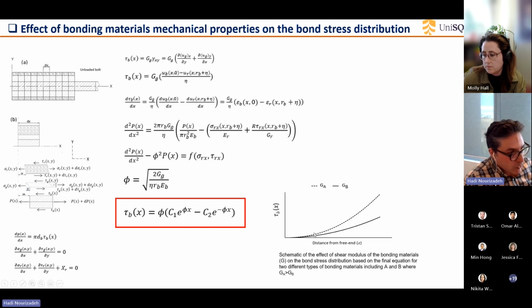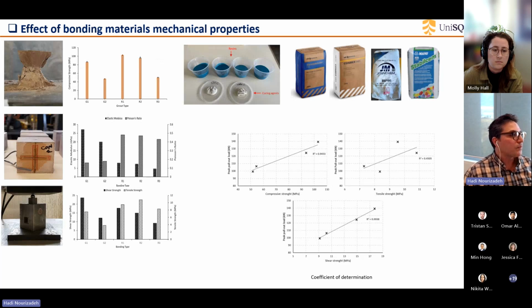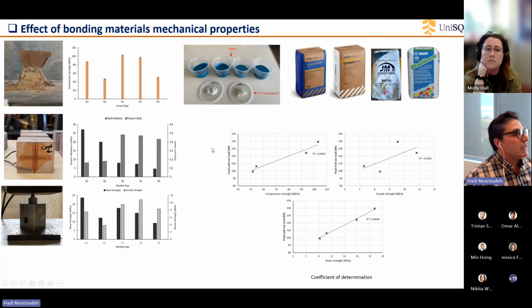This graph also shows that, for the shear stress at a specific distance from the free end, the bolt or the grout with higher shear modulus has higher bond strength as well. We also wanted to know which is more effective: the compressive strength, shear strength, or the tensile strength.